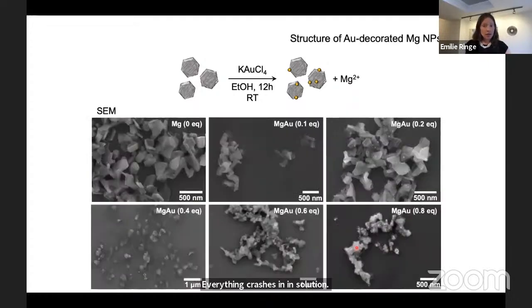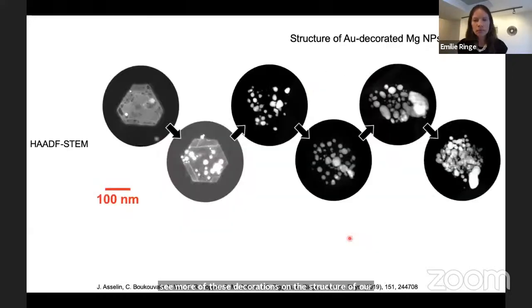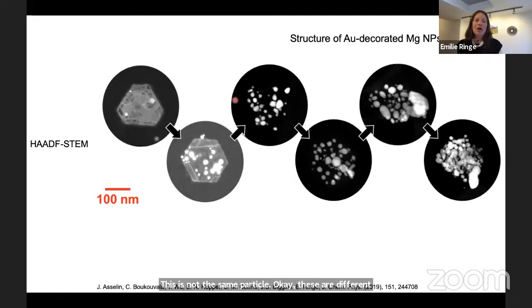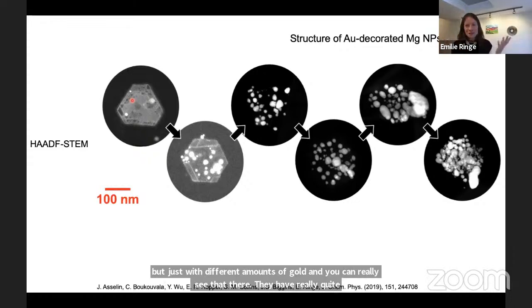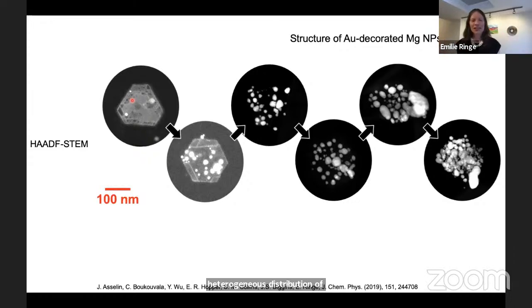These decorations are indeed not an alloy and not a shell. They form small sort of peppered decorations on the structures. This is not necessarily bad news, it's just a bit different. Again, as we put more gold, we see more of these decorations on the structure of our magnesium. This is not the same particle, okay, these are different particles, but just with different amounts of gold. And you can really see that they have a really quite heterogeneous distribution of these gold structures.